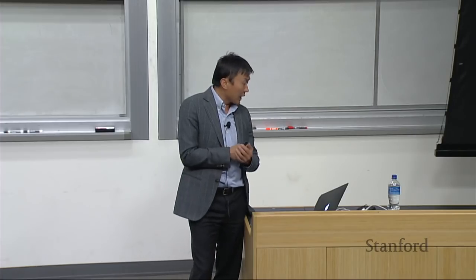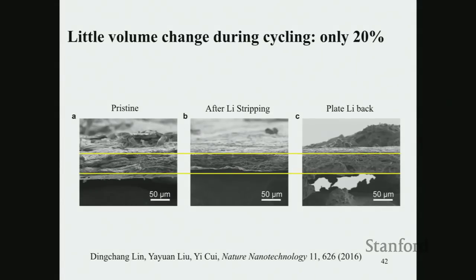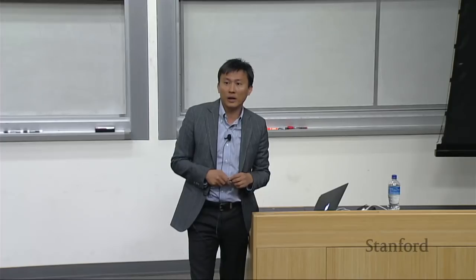And as we said, with this type of lithium hiding between the graphene oxide, if you look at the cross section of this whole film and you strip lithium away completely, it only shrinks its thickness by about 20%. So it's now a lot more stable instead of becoming completely empty. You have a whole structure that could stabilize this metallic lithium. You place it back, and it comes back to the initial thickness.